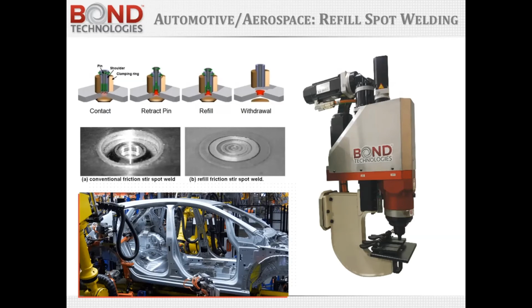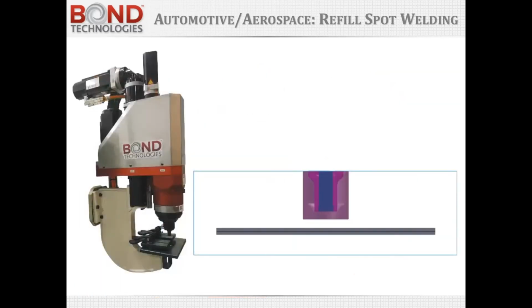And the first thing that happens is that the shoulder descends into the material to cause a lap joint to be welded, while the pin retracts vertically to absorb that displaced material. Then essentially in the refill step, they trade places, and what you're left with, shown in the picture of the weld, is a lap joint that has a flush top surface. So here's a little demo of how this works. The clamp ring comes down, the shoulder and the probe make contact, the shoulder goes into the part, the probe comes up, the probe goes down, the shoulder comes up, and then it removes itself. All this happens, it's already competitive with resistance spot welding and self-piercing rivets.